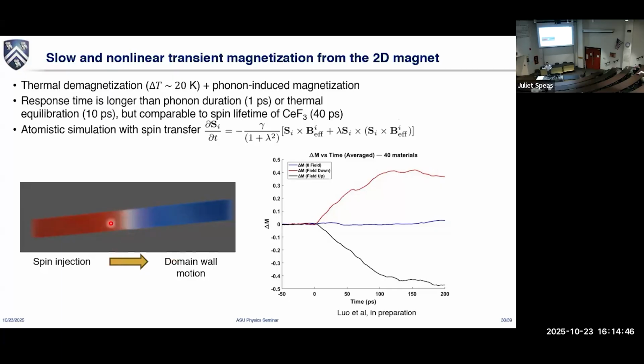And then that movement of domain boundaries is persistent, okay? So can you imagine that, once the pulse comes, the domain boundary moves and it stays there, right? Pretty much like even when the field is gone, it still stays there, right? So that kind of time dynamics agrees better with our observation, but we're still trying to make it a quantitative agreement at the moment, okay? But we're pretty sure that it's a pretty complicated phenomenon. We have chiral phonons, we have ferromagnetism, and we need domains, which is a key part of any spintronics.